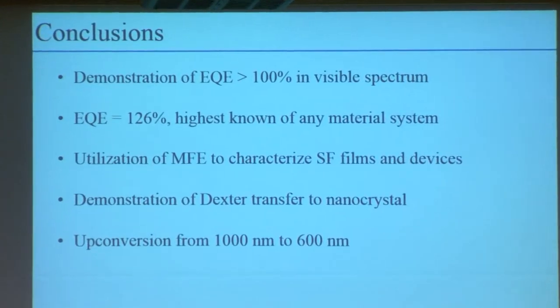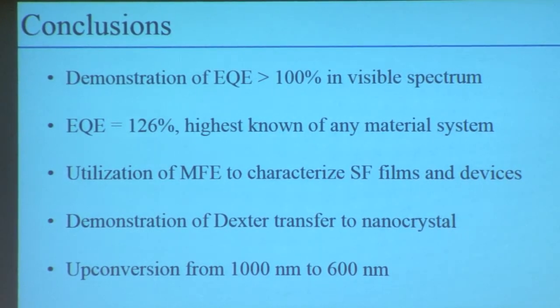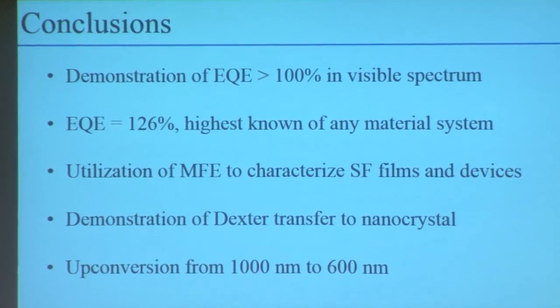We demonstrated an EQE higher than 100%, showing that singlet fission is really a very useful process for us to proceed with. We used the magnetic field to characterize thin films in the devices, and we demonstrated Dexter transfer of this triplet exciton to the nanocrystal, and finally demonstrated upconversion from over 1,000 nanometers to 600 nanometers.